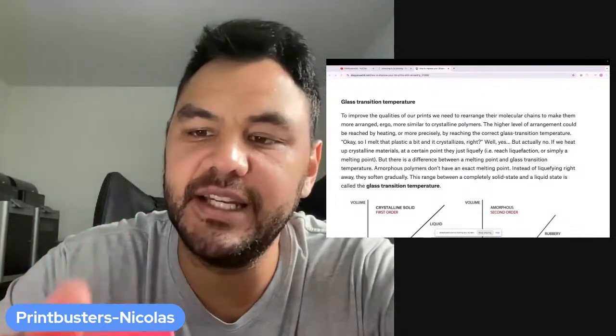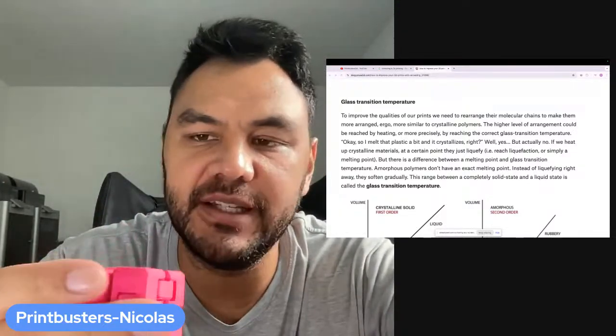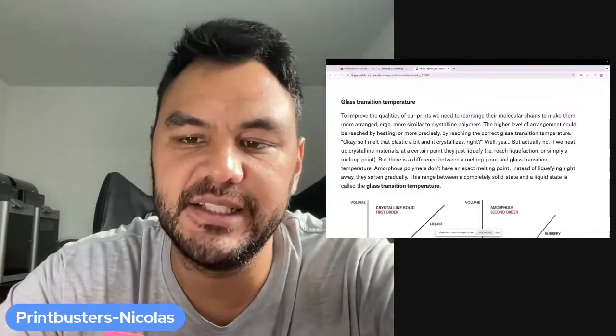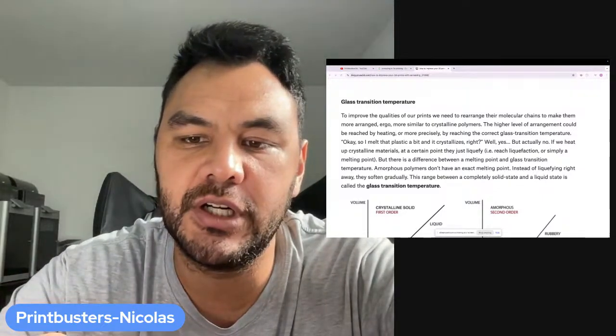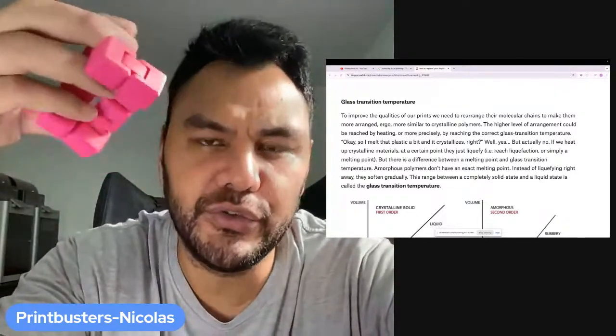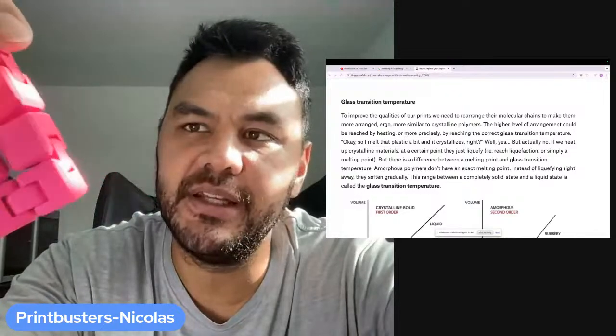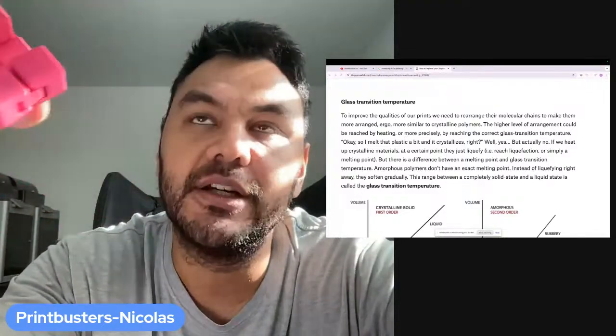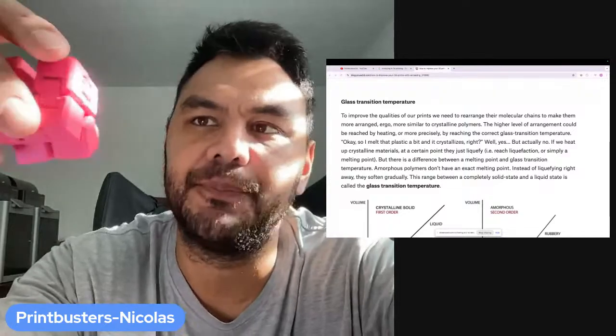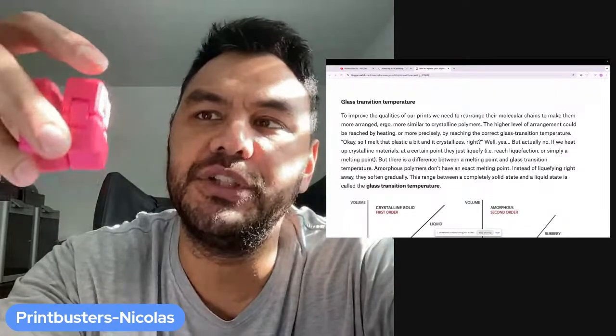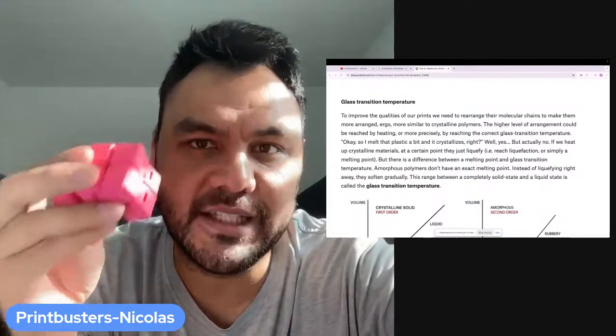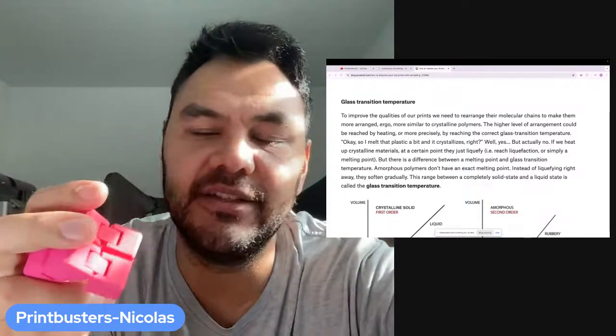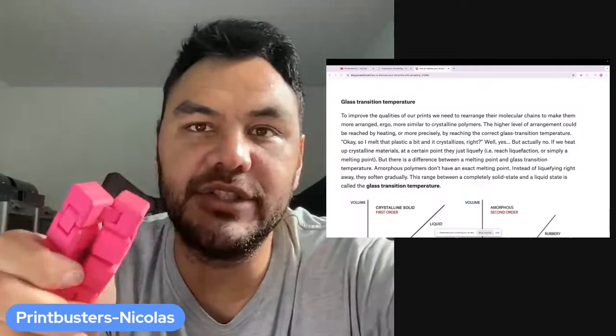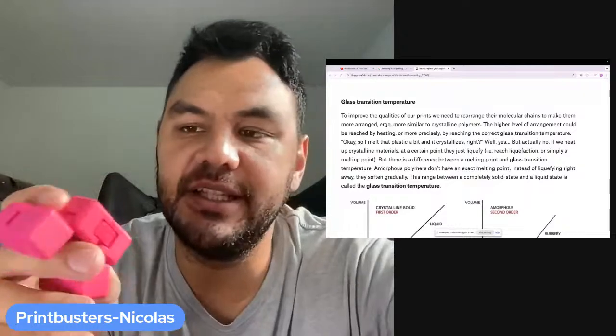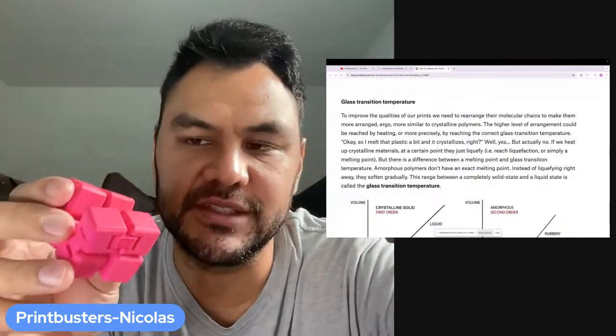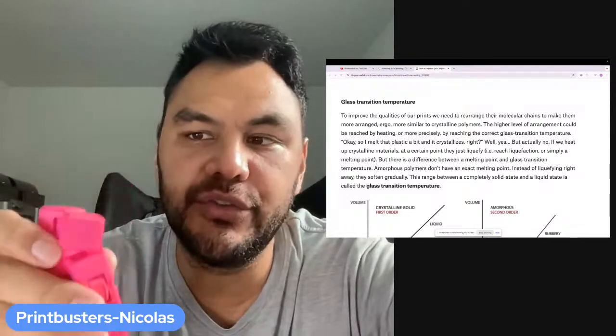But some PLA, what they do is they modify them. I don't know the details, but basically they are creating some, how do you call that, nucleation points, I think, so that it helps the polymer to crystallize during the printing process, which means that after the printing, it will have a slightly higher degree of crystallinity than if it wasn't modified, and that crystallinity degree that is higher than zero is going to give it a little bit more heat resistance. That extra heat resistance will allow you to anneal it even more.